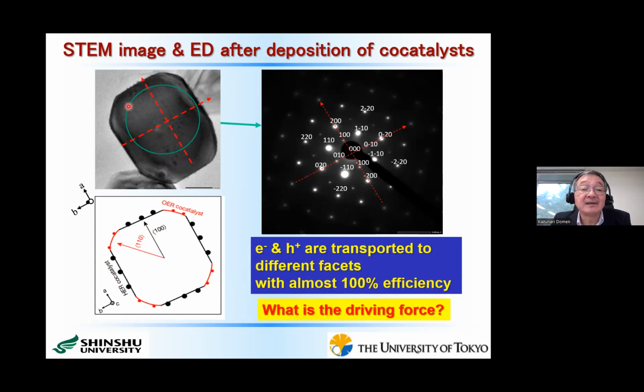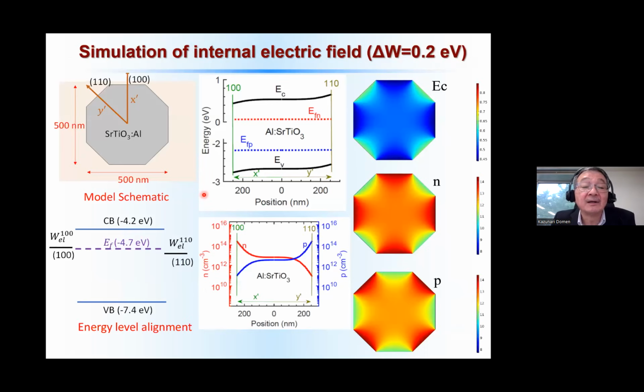We consider that there should exist some internal electric field inside this particle, but the particle size is about a few hundred nanometers, so it is almost impossible to measure that internal field experimentally. So we decided to carry out a simplified two-dimensional simulation of such an internal electric field. This is our model structure. The particle size is 500 nanometers. Here we have the 100 facet, and this is the 110 facet. This is the X prime axis. This is the Y prime axis. And then we assume that the work function difference between the 100 and 110 facets is 0.2 eV. That seems to be reasonable from literature values.